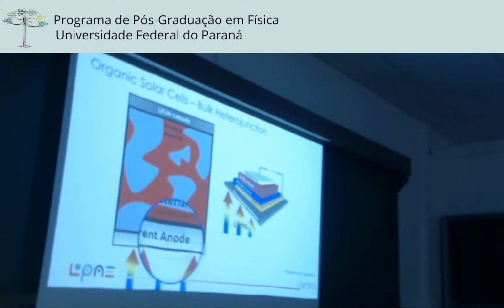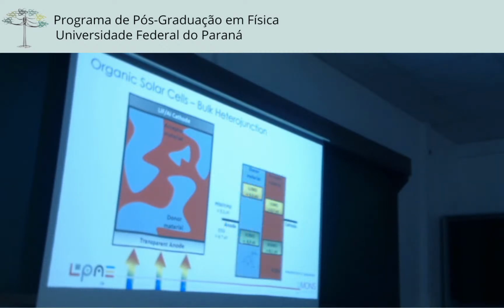So we are blending the system here with the donor in blue and acceptor in red. We need some electrode, of course, and some transparent substrate because we need the light shining on the sample. We have here the electrode, the cathode, and so on, and we can start to measure. So what happens when we switch the light on? We have, of course, the PEDOT:PSS on one side, the P3HT and PCBM, the soccer molecule, the football molecule.